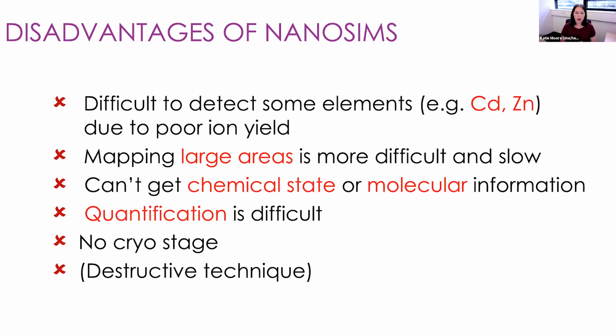I've also written in brackets at the end that this is a destructive technique by its very nature. You saw from that schematic at the start, the ion beam is removing material as we analyze it. So after you've conducted your analysis, you will have a crater on your sample, and that piece of sample will be gone. You cannot go back and analyze it again. So if you want to do a correlative or complementary study, including NanoSIMS, you need to make sure that NanoSIMS comes towards the end of that particular analysis program.